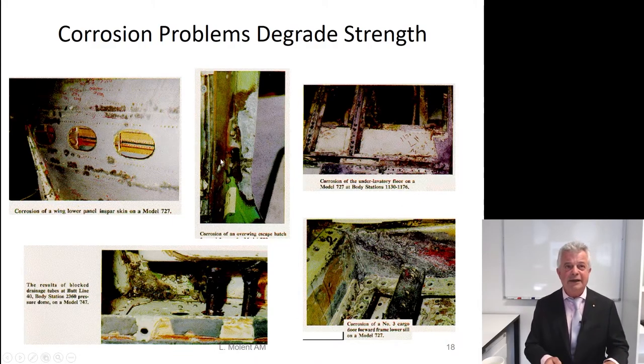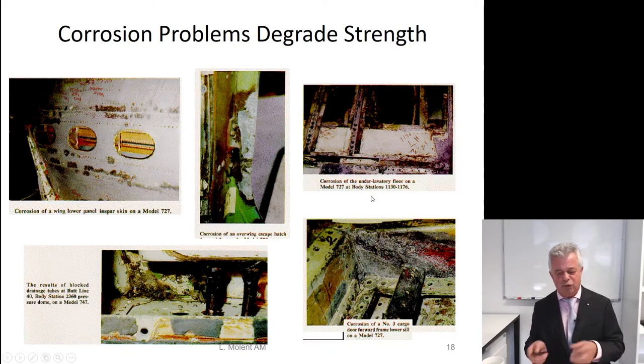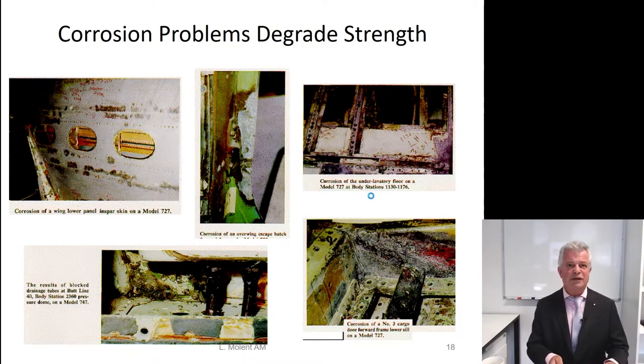Now, what corrosion will do for you, because it eats away material, is that you don't have as much material as the designer thought, so the airplane will not sustain the loads it was designed to because there's not sufficient material in its place. And also, corrosion is a great nucleation source for fatigue, and we'll talk more about fatigue. So corrosion leads to pitting, leads to all sorts of sharp discontinuities, if you like, in the material. Great source of nucleation of fatigue cracks. So why we're so diligent about maintaining the condition of the airplane is to absolutely avoid these type of scenarios. And I can tell you there are many cases where cracking has occurred that led to serious incidents. Or if this was a pressure bulkhead, the pressure bulkhead may fail, leading to decompression, etc. Okay.